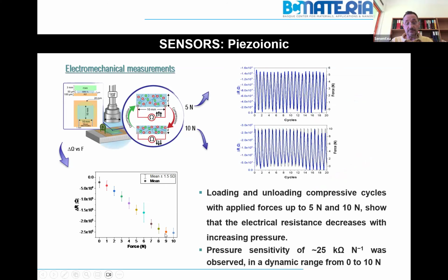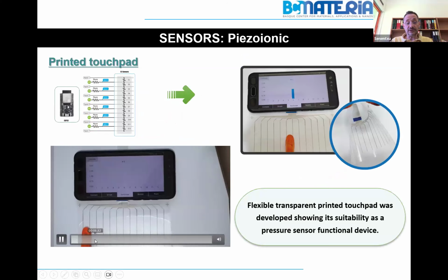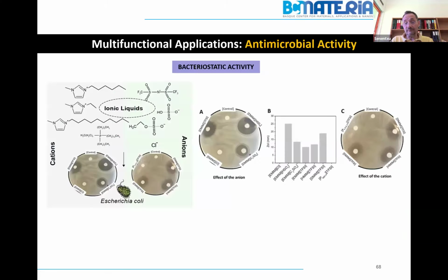And you see that it is proportional to the force and proportional to the deformation. And you do things as interesting as this: a fully transparent printable touch screen based on ionic liquid and whatever polymer you use. It can be alginate, it can be carrageenan, because in this case, the polymer is not active, it's just passive. It's the network that has to allow the proper interaction to the ionic liquid to let it move, but not enough mobility to get out, okay?